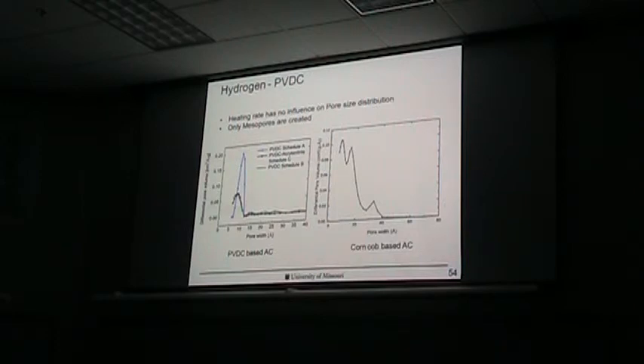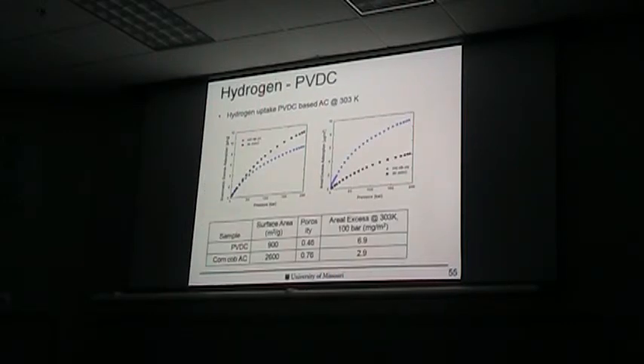And this one is the so-called pore size distribution. That shows you that for PVDC, we have a lot of pores at around, I would say, 11 angstroms. And it doesn't matter how quickly you heat them up, you just end up with 11 angstroms. If you look at the corn cob-based carbon, we have a lot of different pore sizes. We have one here at around 35 angstrom, then around 22, and this is also 11 angstroms. So on the left side, this is activated carbon from corn cob, and this is activated carbon from the polymer.